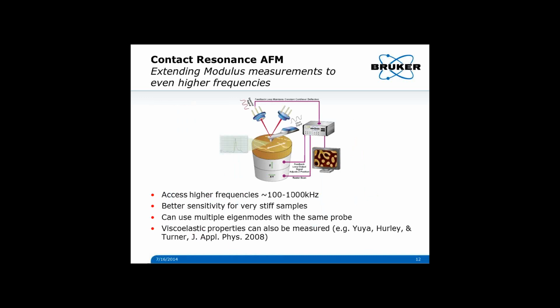Now, what if we wanted to extend to even higher frequencies? Well, we could use contact resonance to do that. Contact resonance frequencies are typically in the 100 to 1,000 kilohertz range, which nicely complements the lower frequency ranges of peak force tapping and force volume. Contact resonance can work with multiple eigenmodes of the same probe, which allows both better sensitivity to stiff samples, but also allows you to work with multiple frequencies with the same probe. Contact resonance can also be used to get viscoelastic properties directly. You can look at this paper by Yuya, Hurley, and Turner in 2008.